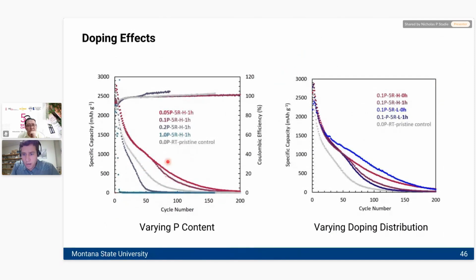This was our first foray into doping, and so I'm going to use this as a good textbook example of how doping can really dramatically change the outcome of results for lithiation. We tried different methods for getting the phosphorus in. For example, we would use different heat treatment temperatures. We have a high and a low here. This high number turns out to be about 1100 degrees Celsius. The low is about 800 degrees.